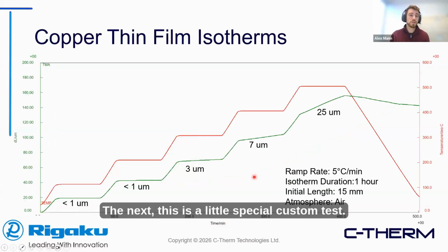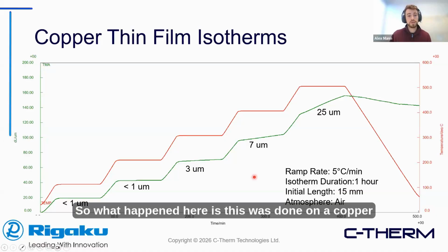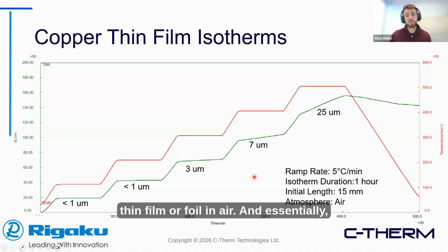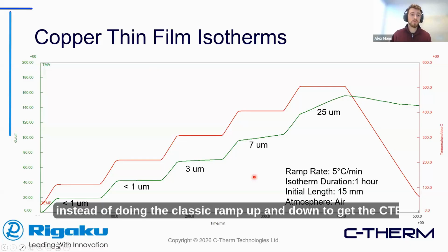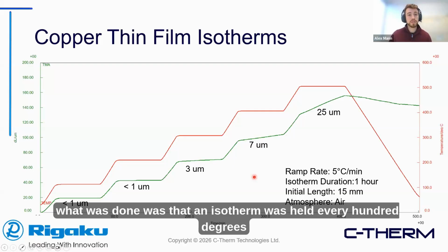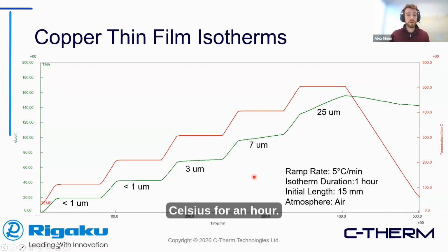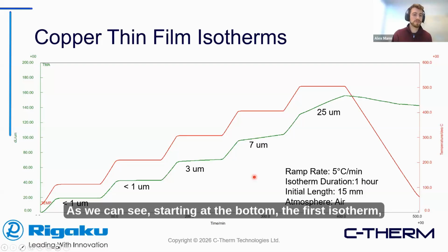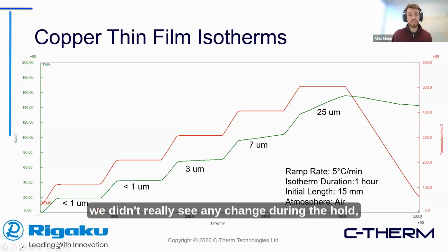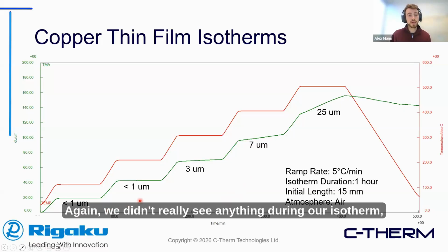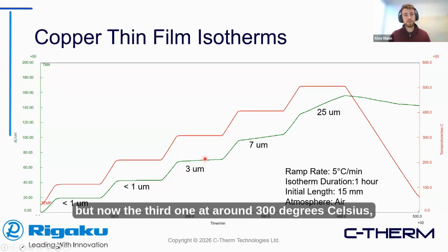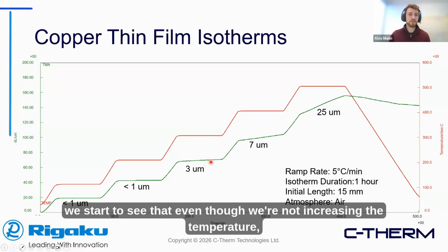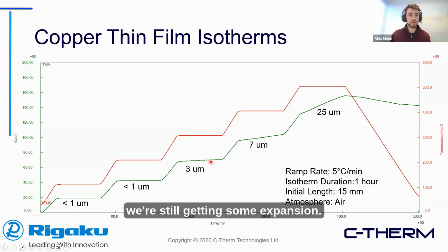Next, this is a little special custom test. This was done on a copper thin film or foil in air. Instead of doing the classic ramp up and down to get the CTE, an isotherm was held every 100 degrees Celsius for an hour. As we can see, starting at the bottom, the first isotherm, we didn't really see any change during the hold, which is expected. As we go to the second one, again, we didn't see anything during our isotherm. But at the third one, at around 300 degrees Celsius, we start to see that even though we're not increasing the temperature, we're still getting some expansion.